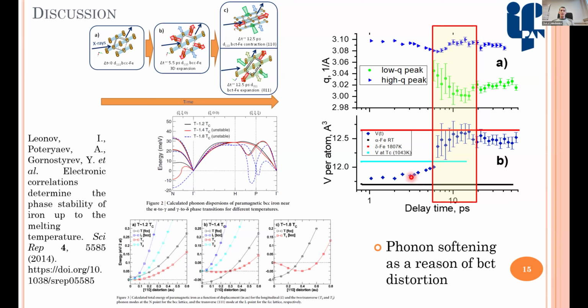So we cannot operate with the Curie temperature, but our results indicate that the lattice expansion, that is, the change of lattice parameters over the value of volume or lattice parameter of the BCC unit cell at Curie temperature, induces distortion of the BCC unit cell to BCT.